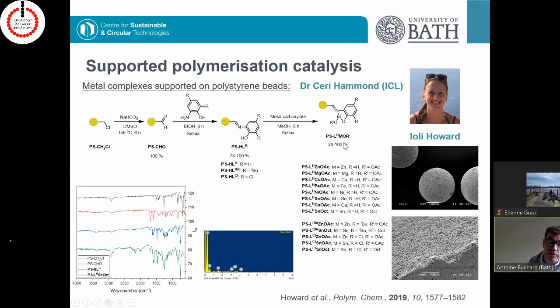And we've been able to produce this wide range of supported metal complexes, from zinc, magnesium, copper, iron, basically everything we had in the lab. The way we characterize those things is a bit more tricky than when, for example, you design a homogeneous catalyst and you want to use it for homogeneous ring-opening polymerization. While we're well aware that those characterizations are not perfect, they were still good enough to make sure that we had made some of those complexes and some of them were supported on those polystyrene beads.